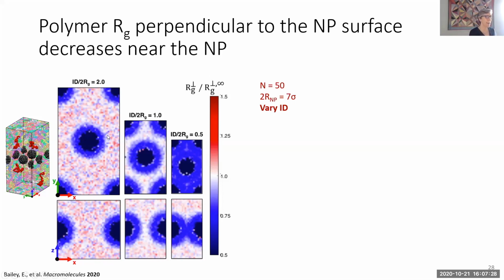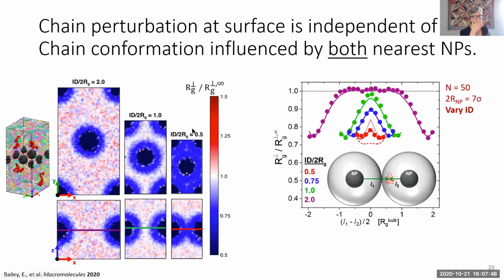And what you'll notice is that the extent of distortion, like the amount of squashing of the polymer chain, is independent of how far apart these particles are, until the blue, this compression zone or this contraction zone, overlaps with the neighboring particle. And we can see that here. So this is all for the same system where we're just bringing the particles closer and closer together. The amount of distortion of the radius of gyration, it's relative to the bulk, it's down by 25%, and that's independent of how close the particles are. So the different colors here are different interparticle distances. It's the same RG for all of these data sets.